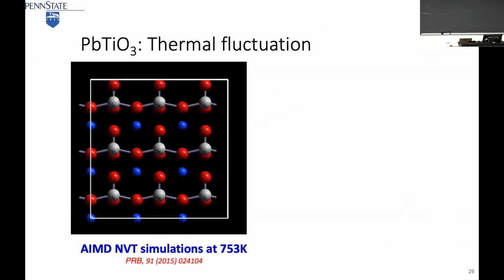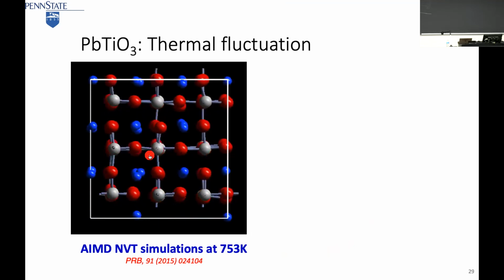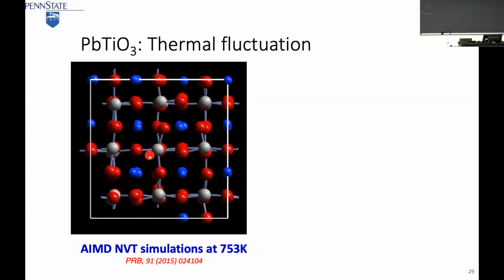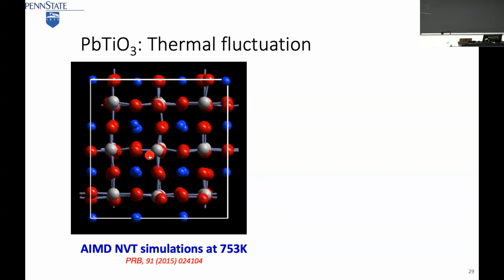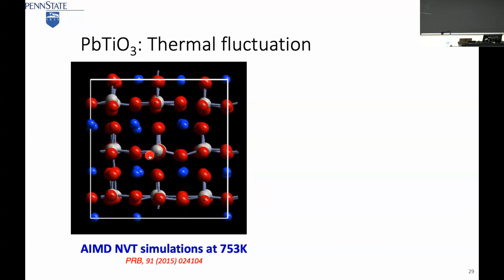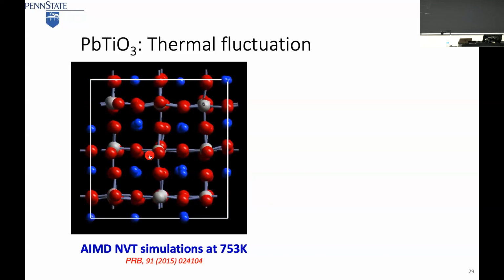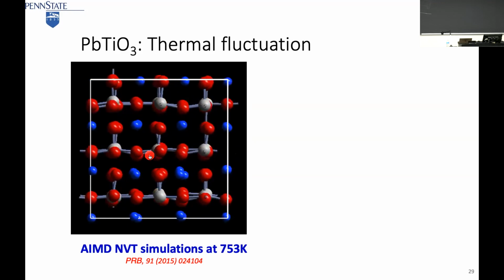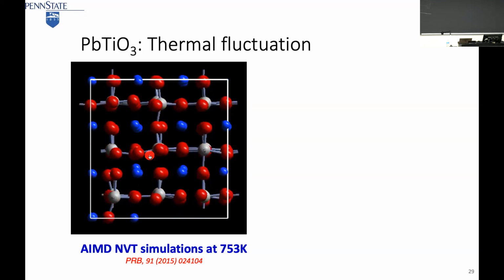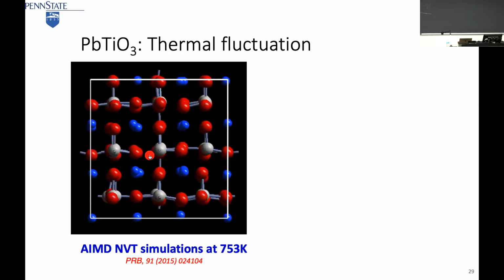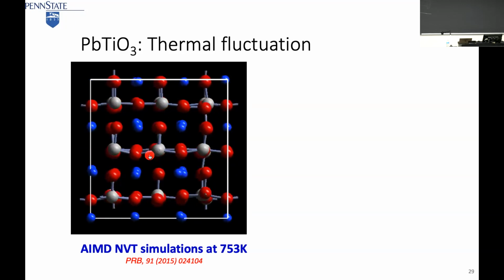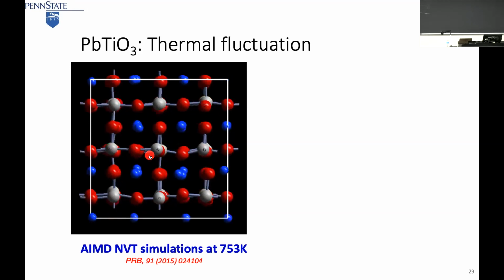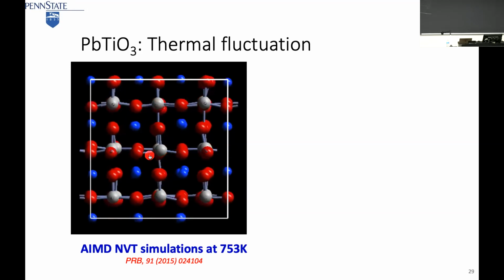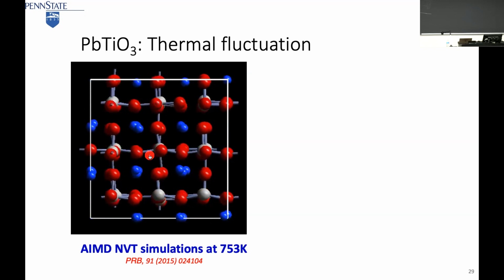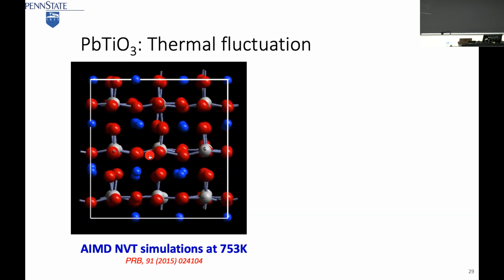All right. So let's go back to this problem. So this 753 is right at the transition temperature on the tetragonal to cubic transition, by X-ray. So we fix the shape, the white cubic, from the experiment data, the lattice parameter. Then you heat it up to 753, and then you see the atoms here. The blue atoms are the titanium ions in the middle. You see the blue atom moves up, moves down, and moves. Of course, it looks very slow, but actually it is very, very fast.